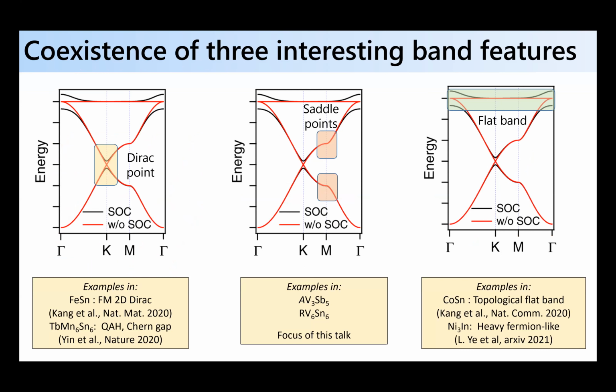If you look at the coexistence of these interesting band features across the literature in recent years, there have been a lot of experimental studies, for instance, looking at kagome metals like iron tin or terbium manganese 6 tin 6, where there are large anomalous Hall effects derived from the Dirac point in the compound. Basically, it gets gapped out via spin-orbit coupling. You have a large Berry curvature and a large anomalous Hall effect in those systems that are magnetically ordered.